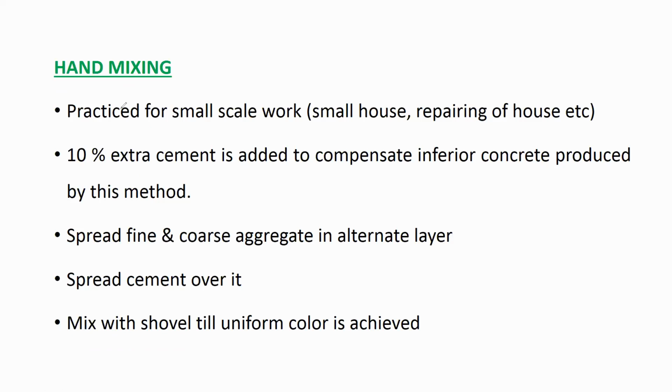Hand mixing is practiced for small scale works. Hand mixing of concrete is used for small scale works, like construction of a small house or any repair work. Ten percent extra cement is added to compensate for the inferior concrete produced by this method.